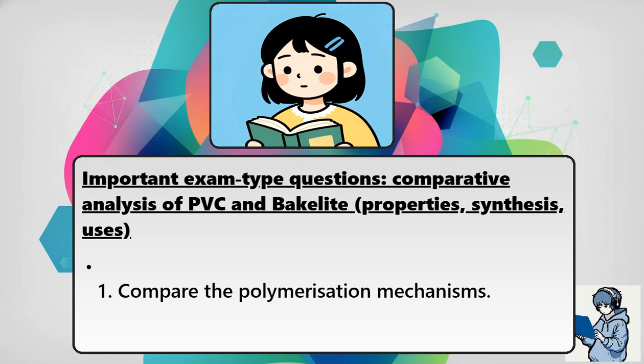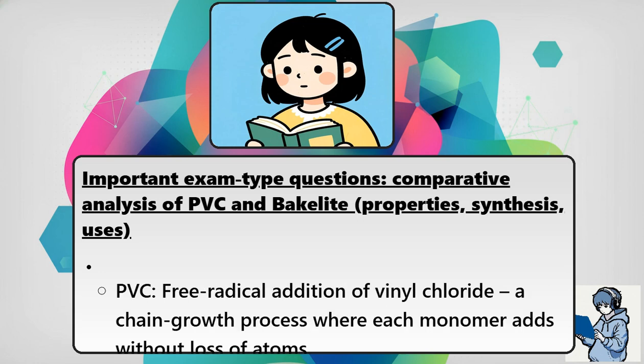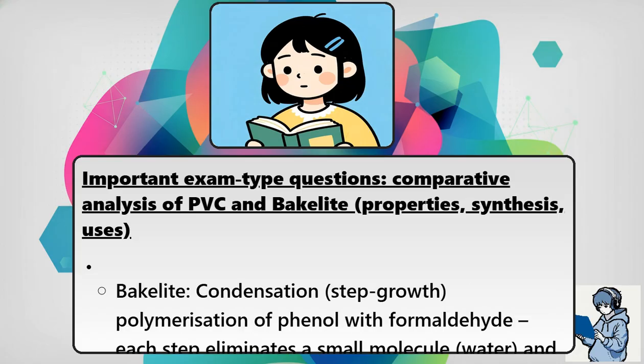1. Compare the polymerization mechanisms. PVC: free radical addition of vinyl chloride, a chain growth process where each monomer adds without loss of atoms. Bakelite: condensation step growth polymerization of phenol with formaldehyde. Each step eliminates a small molecule, water, and builds a three-dimensional network.